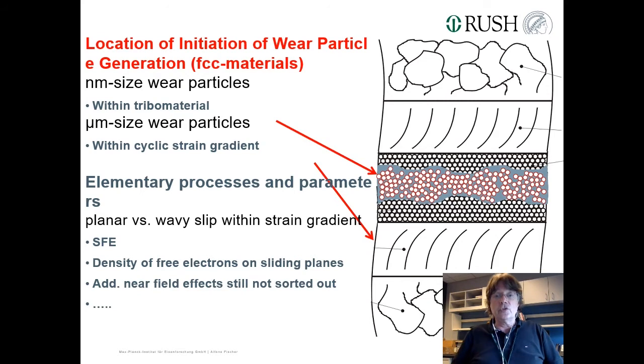We were able to sort that out, let's say, in a first rough approach. I thought it's the stacking fault energy, which is not the full message. The full message is it's a ratio between the density of free electrons on the sliding planes divided by the stacking fault energy. So this has been sorted out pretty well for copper-based alloys. There are still some near-field effects which contribute to that, but I have not been able to sort that out. And whenever I talk to real fundamental material scientists, can we do something on near-field effects, they run away. So if you know somebody who would be interested in doing something down here, please write an email.